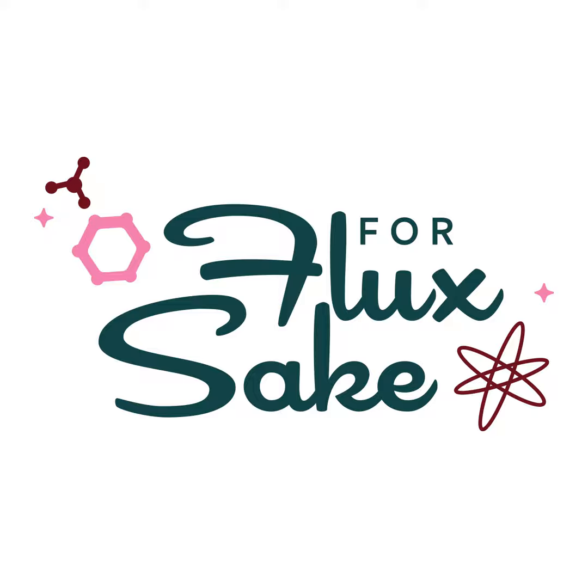What crazing is, and everybody again has their own impression and all that, but there is only one cause of crazing. So let's just set that out. Crazing is caused by this concept of thermal expansion. And we mention thermal expansion on the show all the time. And that is that every single material on the planet, not just ceramics, but metal and concrete, whatever, they all expand when you heat and cool them. The problem that we have in ceramics is that your glaze is going to have a thermal expansion of X, and your clay body is going to have a thermal expansion of Y. If the difference between X and Y is too extreme, the glaze is going to crack to relieve the stress.